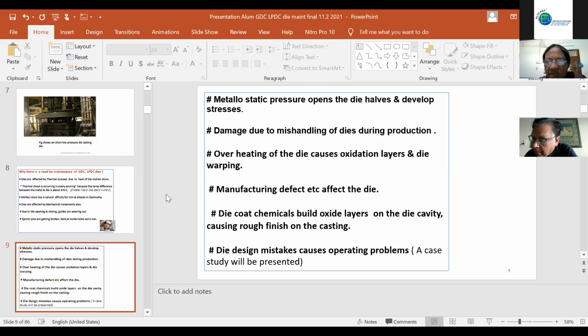Damage due to mishandling of dies during production also happens. Overheating of the die causes oxidation layers and die warping. Sometimes when the dies are heated to start the pouring, people put the burner on and go off. The dies will get red hot.